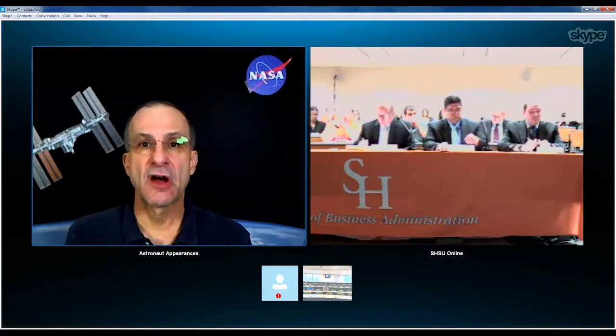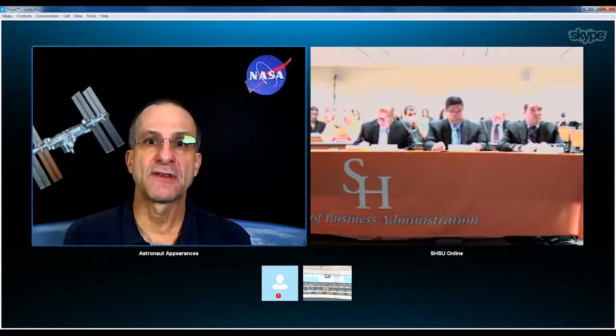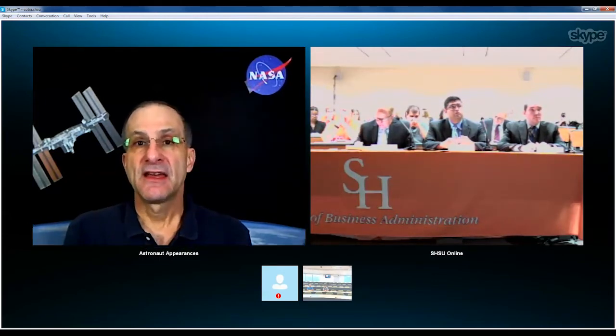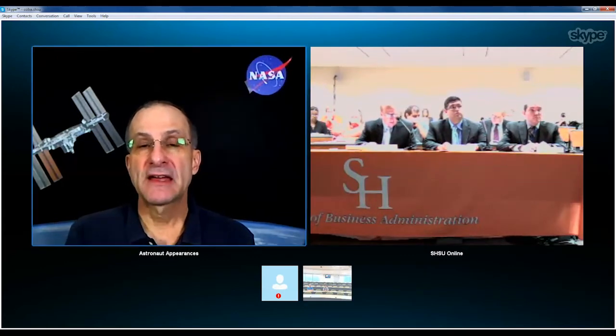its color is kind of a dark green, and that comes from the silicon carbide particles that you put in there, and it's thick. You could take a dollop of it and put it on the table. Say if you had something about 20 millimeters in diameter, you could pile it up into a little stack, and it'd probably be 20 to 25 millimeters high. So it's not a liquid that, if you put it on the table, would kind of run out into a thin pancake. I guess the best analogy is the spackle compound that you use plastering walls, and the compound used with seam tape when you put drywall together.